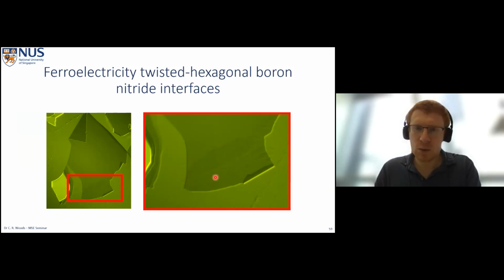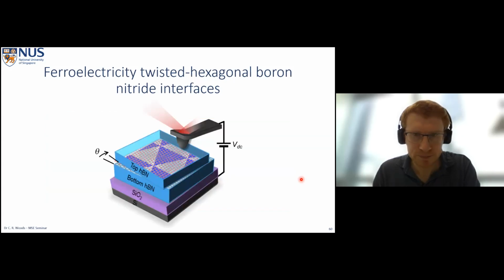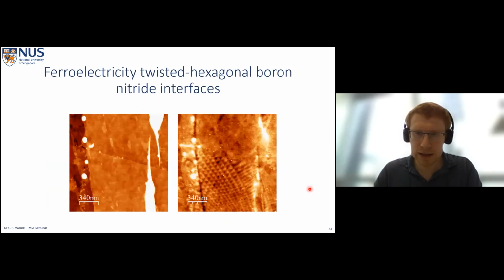But what we've done here is we found our monolayer step. We got another boron nitride. We put it on top of the monolayer step in the bottom boron nitride. And now we're going to do some electric force microscopy. I described the operation of this before when we were looking at piezoelectricity. And let's see what we can see. Okay, so we see something like this.